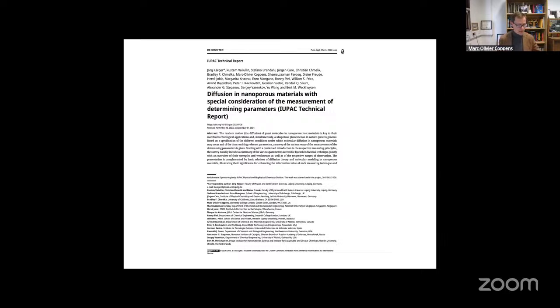So for a gas in Knudsen diffusion, the mean free path, which you can also calculate, can be related to physical chemical properties of that fluid. When the mean free path is much larger than the local pore diameter, which you would get from a pore size distribution measurement, then you are in the Knudsen diffusion regime.